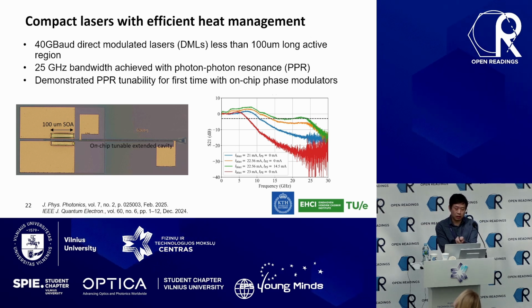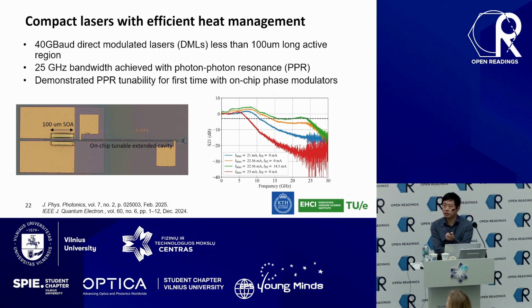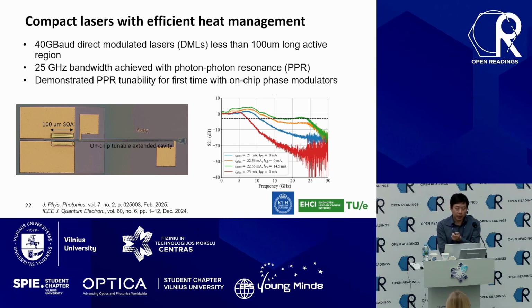If you look at the graph on the right side, we see at around 7 to 8 gigahertz position, we have a resonant peak. And this is the relaxation oscillation of my main laser cavity. Yeah, it's determined by my laser cavity length. And then at around 25 gigahertz, you see that from the red curve to the green curve, there's a second peak rising up.